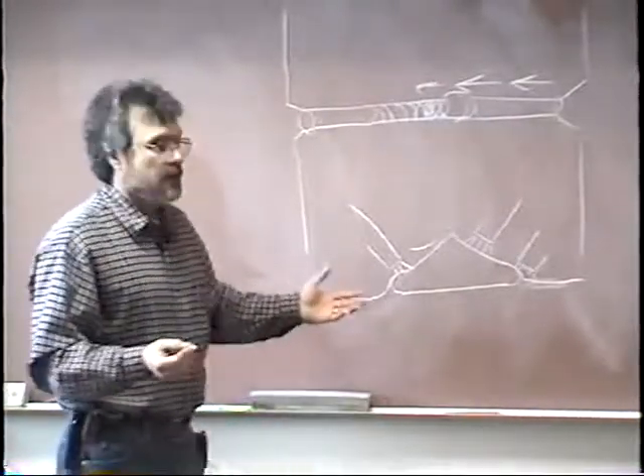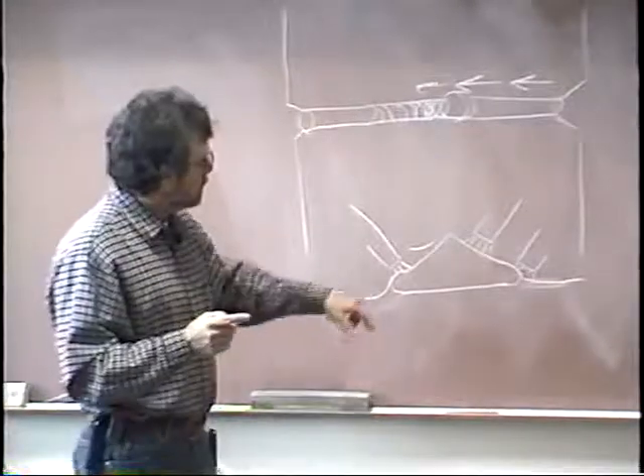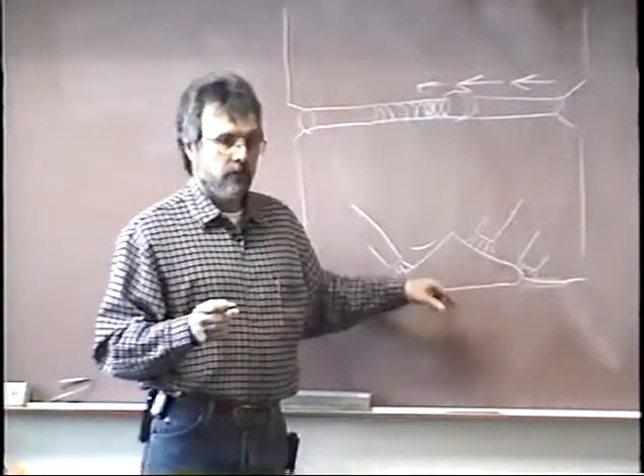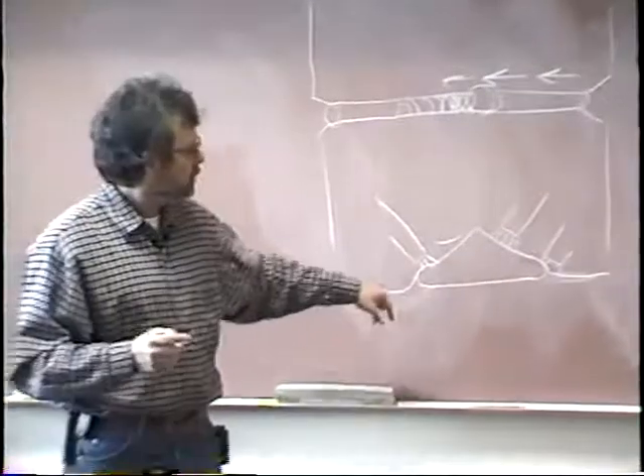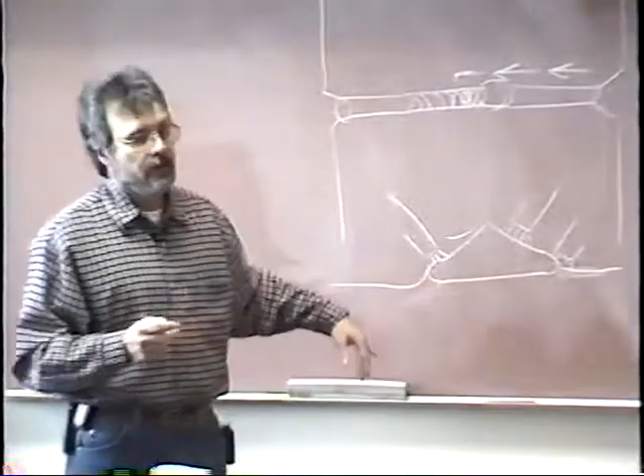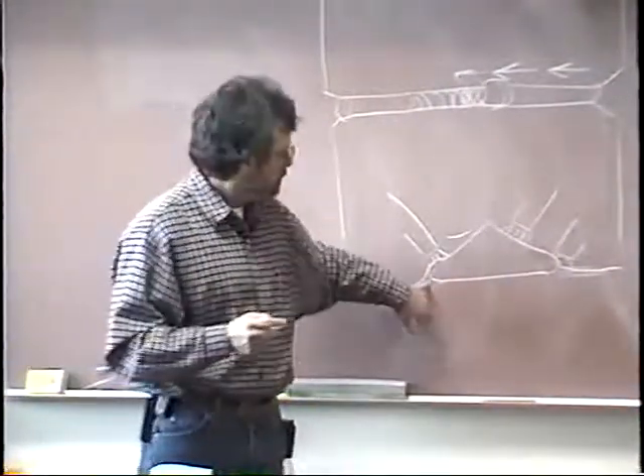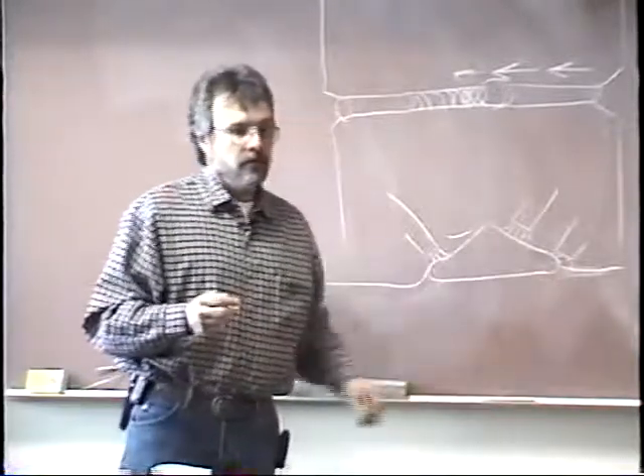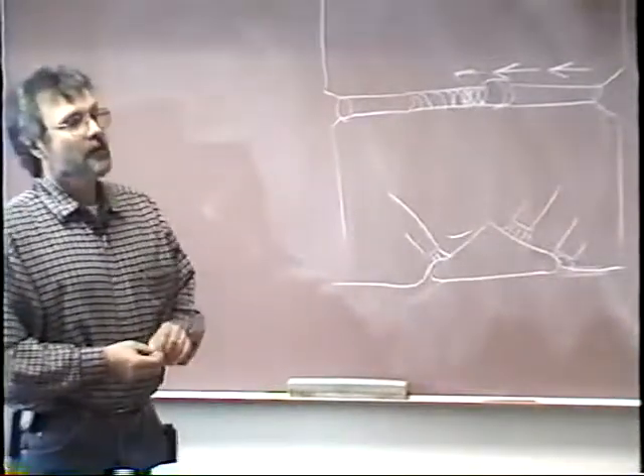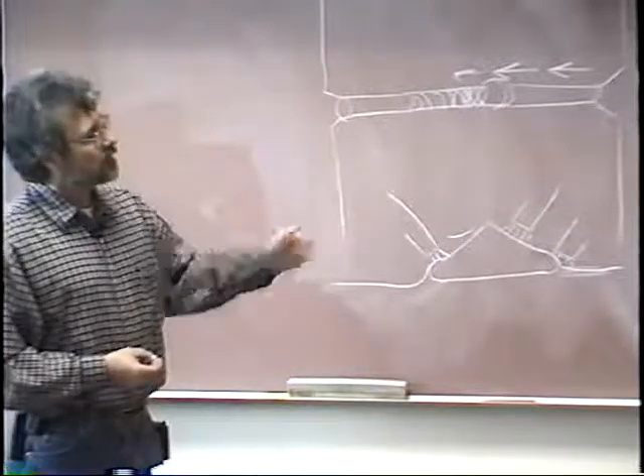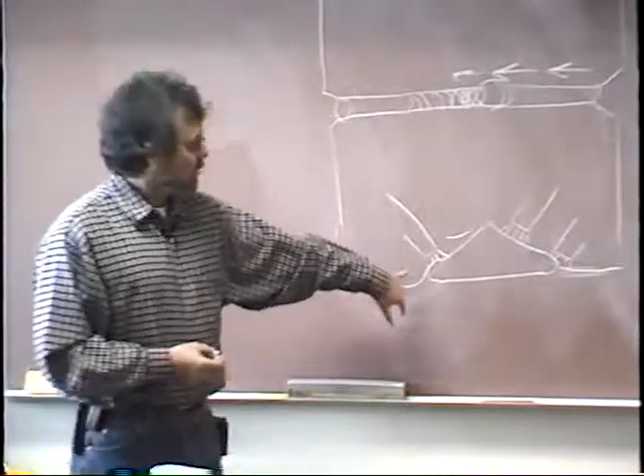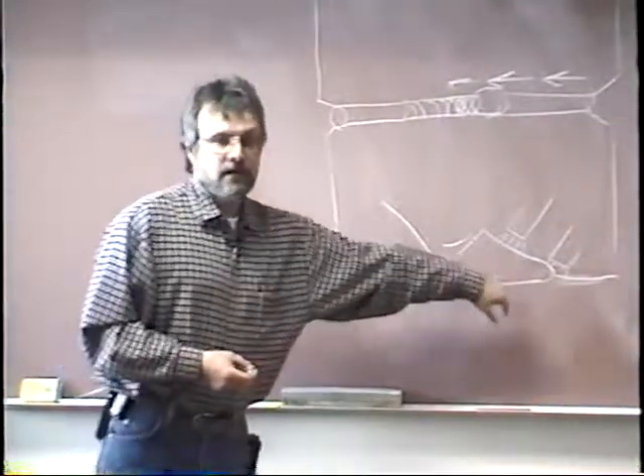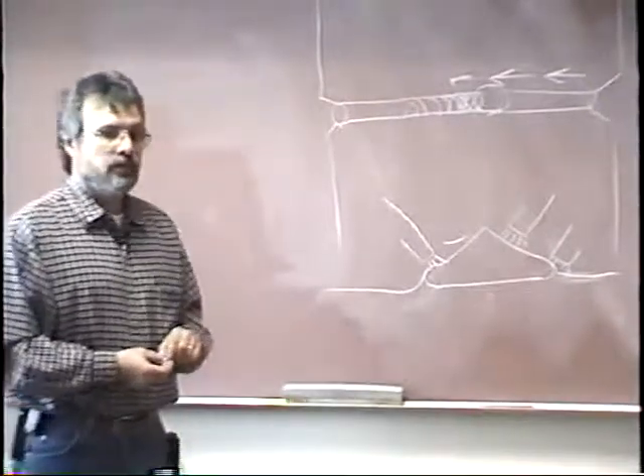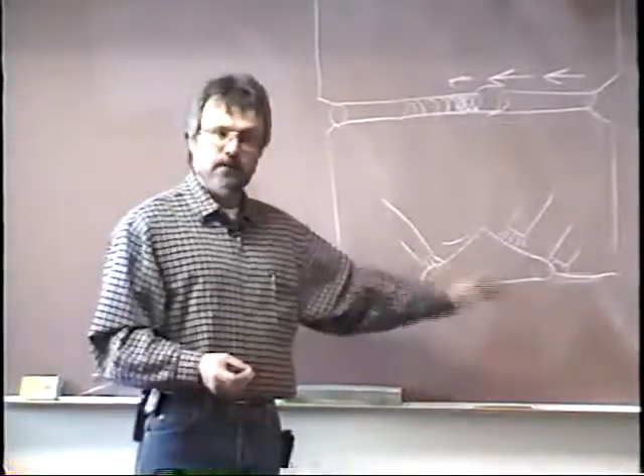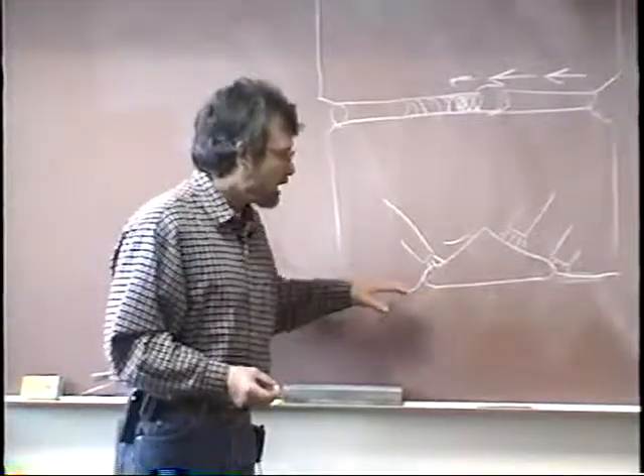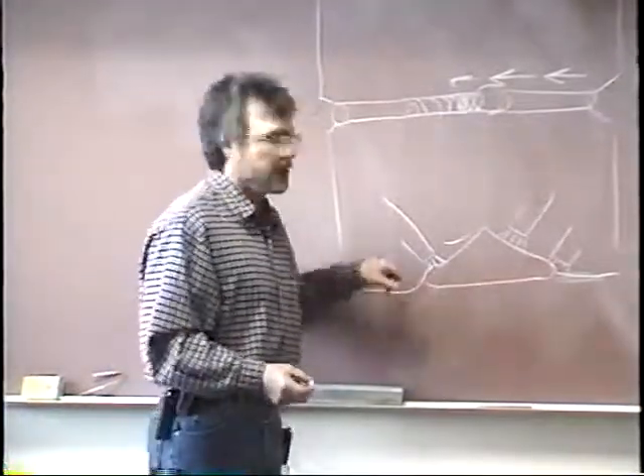And those are all good techniques, but the key is still proper preparation of the tack before you ever start. If you feather those tacks down to a fine razor edge, you're not going to have any problem with these toenails. And like I've said before, most welders I've failed on visual has been internal undercut. But the second most thing are these tie-ins on their tacks, because they just don't get proper tie-ins. Always remember that the tack becomes part of the weld. And you've got to have thorough fusion between the tack and the weld bead.